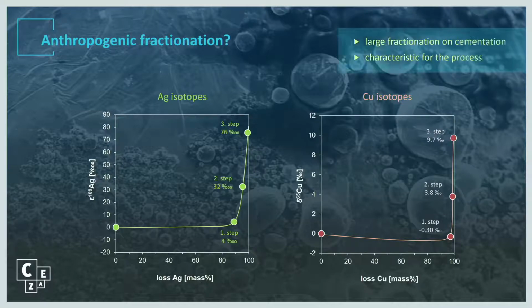And when you compare this with the natural variation of silver isotopes in gold ore, you see these isotopic values are far beyond natural variation of gold ores, and so it seems possible to recognize the cementation process by analyzing the silver isotope composition and the copper isotope composition.